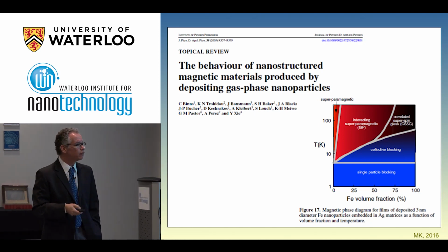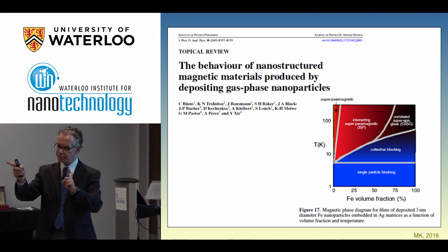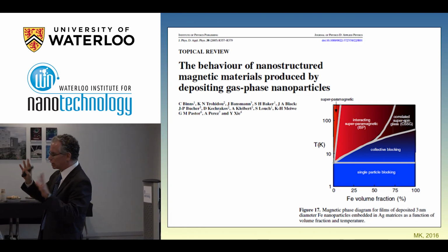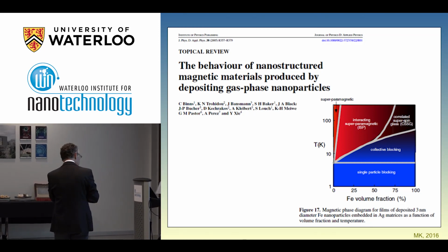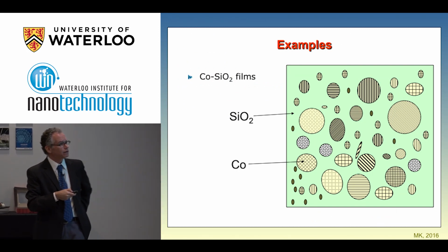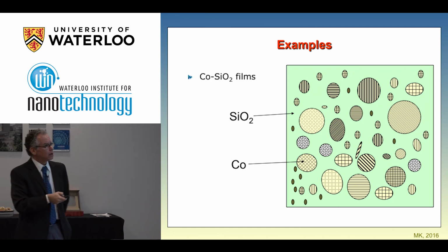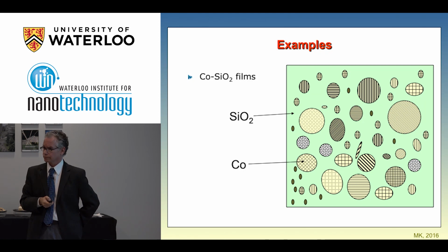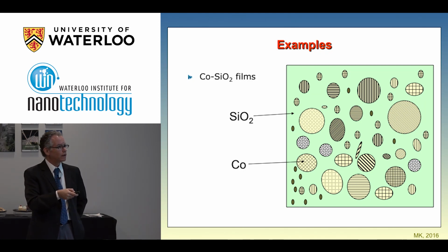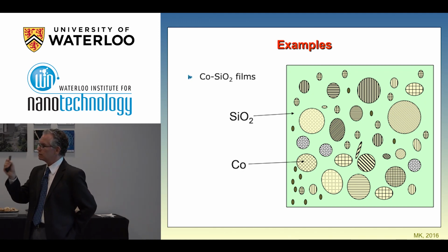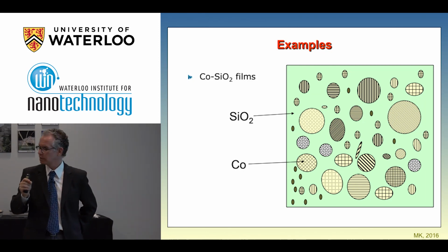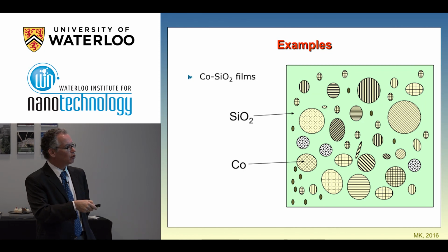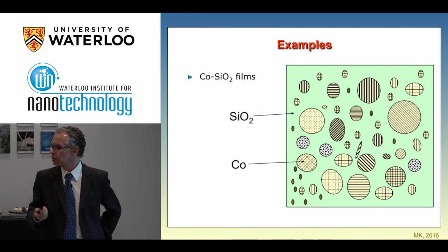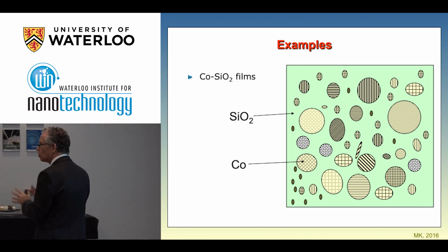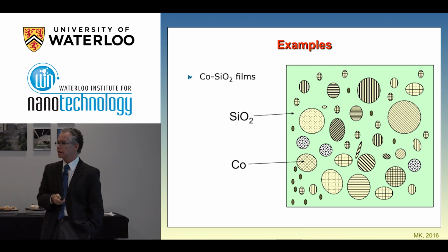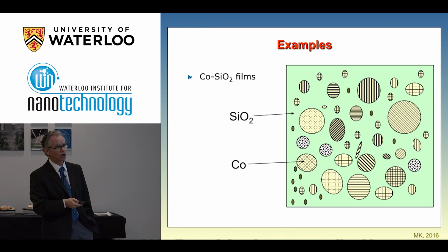So I mentioned a little bit before of what happens whenever you have a system of magnetic moments which are completely separated to each other. But of course, there is an interesting thing, that this is in fact exactly what I study. Each single element here is magnetic. So you have a cobalt, another cobalt, another cobalt. Each magnetic element is a sort of tiny magnet. So even though we have an insulating matrix, they interact to each other through dipolar interactions. So it's an extremely complex system which they have dipolar interactions among each other. So this is the kind of system that we don't understand very well yet.